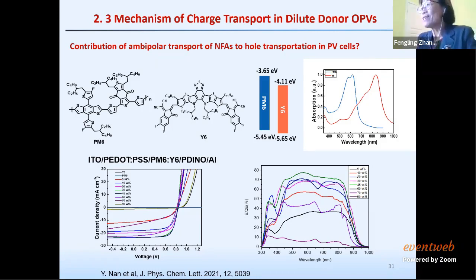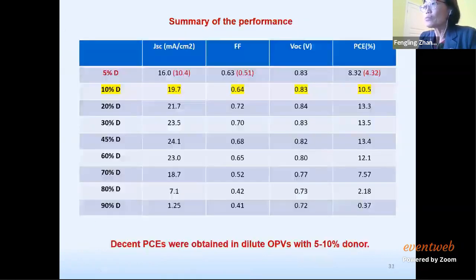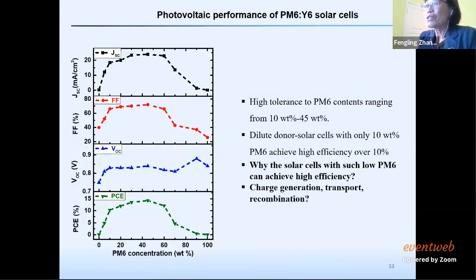So here we make devices. We also use a diluted structure because we want to show the acceptor influence instead of the donor. So EQE and IV are shown here with different percentages of donor. Here we summarize the efficiency of the device. I highlight the 10% donor. You see the 10%. Before we made the device, we never imagined we could get 10% efficiency with such a small amount of donor. So this shows the variation with the percentage of the donor.